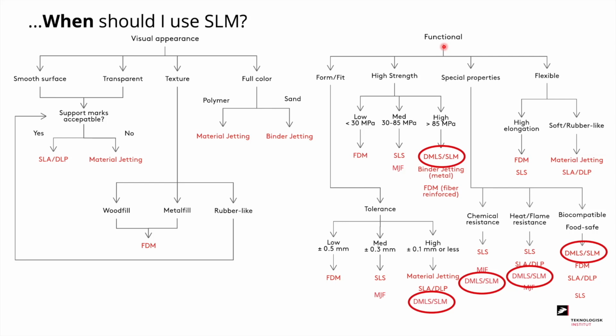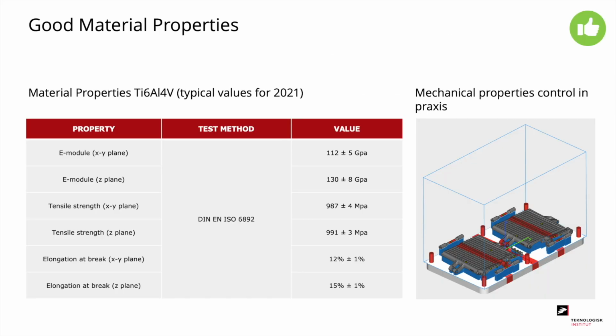The SLM process is definitely only used for functional parts, as it has the highest mechanical strength. It has the best tolerances, and it is resistant to chemical and heat, and it is biocompatible. So for SLM parts, the material properties are good. The values are listed here, and as you can see, there are very high tensile strength, decent elongation, and these are typically valued for titanium.